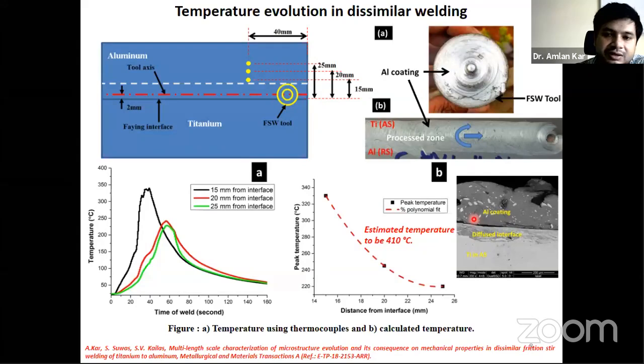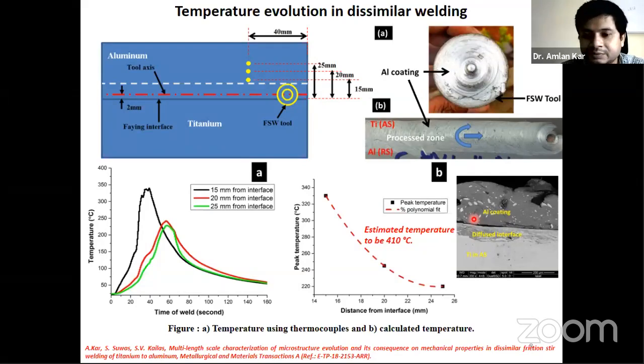If titanium interacted with the tool, then we could expect the temperature to be as high as 1000 degrees centigrade, and at that temperature aluminum should basically melt. But we have not seen any melting over here. So what is the reason? The reason is there is limited interaction or no interaction, because of the formation of the aluminum coating. At this temperature of 410, which is actually the lower limit, aluminum is recrystallized and much plasticized, and because of the higher plasticity of the aluminum, it squeezes out of the welding zone and forms a coating on the surface of the titanium.